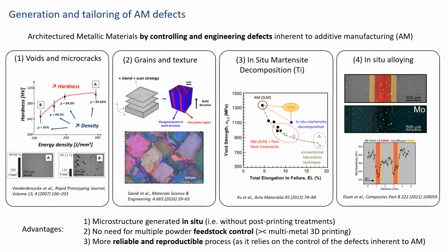So there are different defects and thus different strategies that we can use in order to introduce variability of material properties within the 3D printing process. The first and most classical one are voids and microcracks, and these defects can be used because the voids, for example, introduce locally a softening effect, and that means that we can create interfaces with lower yield stress as compared to the matrix.